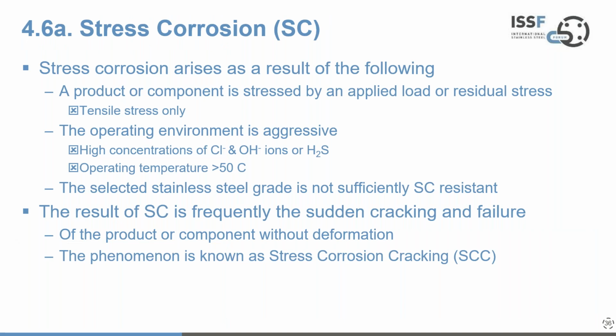So finally in this section, I'd like to move on to stress corrosion, which is an interesting and yet frightening aspect of corrosion. And it generally arises as a result of the following thing. The product or component is stressed by an applied load or a residual stress, and we're talking tensile stresses only here, not compressive stresses. The operating environment is aggressive, and that can be high concentrations of chloride, hydroxide ions, hydrogen sulfide, and the operating temperature in that environment is greater than 50 degrees centigrade. And the third dimension is the selected stainless steel grade does not have sufficient stress corrosion resistance.